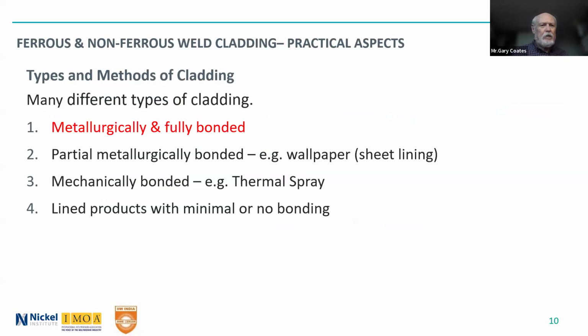It's important to understand that there are different types of cladding, and we talk about metallurgically and fully bonded, and that's the one I'm going to be talking about, and weld clad falls under that category. Partially metallurgically bonded: if you do a sheet lining, you line a tank with a thin layer of stainless, that we call partially metallurgically bonded because you're welding it in certain spots, but it's not totally bonded. Mechanically bonded, a good example of that is a thermal spray. Thermal spray does not metallurgically bond the thermal sprayed material to the backing material. It works in many cases, but not always. And then there are some lining products with minimal or no bonding at all. But we're going to only talk about the metallurgically and fully bonded materials.